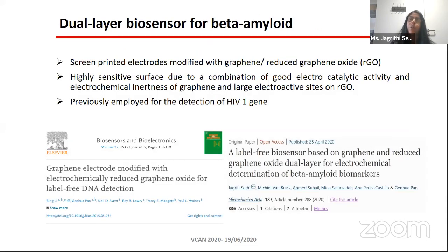So what is special about our biosensor? We made this dual layer biosensor using graphene and reduced graphene oxide. We did that because we wanted to combine the high sensitivity of graphene with RGO, which has high electroactive sites. So the combination of the two provides really high sensitivity as well as electroactivity. The electroactivity problems of the graphene biosensor can be overcome by combining both graphene and reduced graphene oxide.